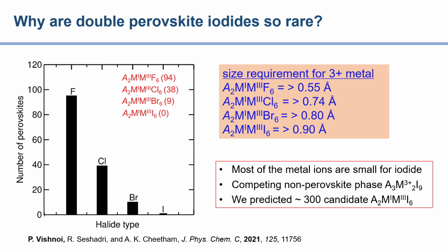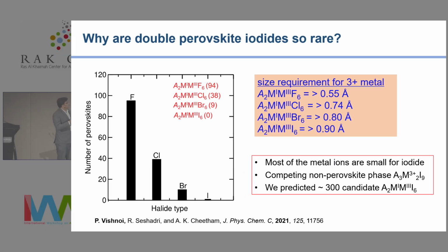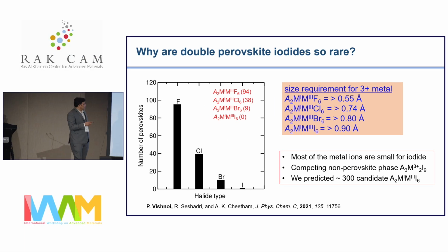So while doing this, as I mentioned, we looked at about 150 structures in various crystallographic databases. And then we segregated the structures based on halides. What we found is the majority of the structures were fluoride-based double perovskites, and then the number drops. And by the time we are at iodide, there's no compound known. So then we wrote this paper, why iodide perovskites are so rare.